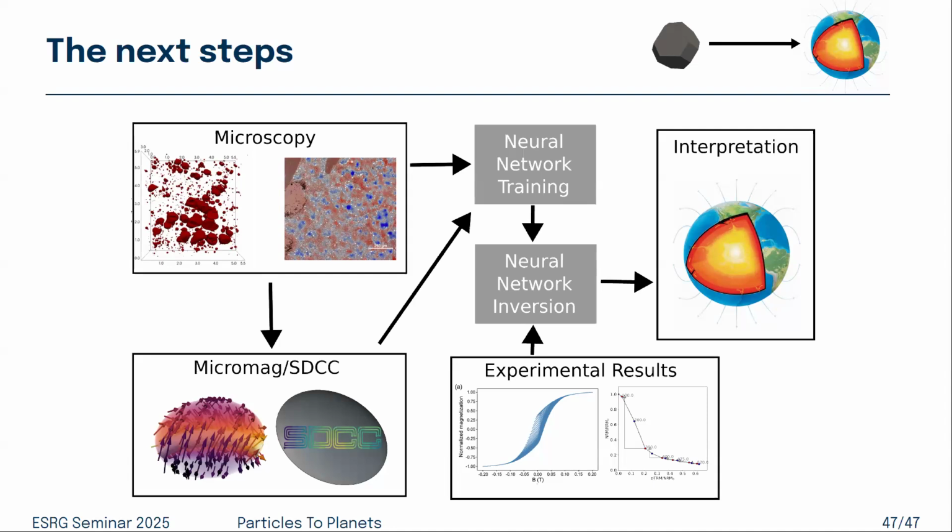The resolution is not nanometers for those things. But what's quite useful is you can identify regions of interest in your sample using one of these broader scale magnetic techniques that tells you what your magnetization is doing, and then go in deeper with something like FIB slice and view, and get out what grains are directly responsible for that. So there's some pretty powerful things that I think you can do with that.